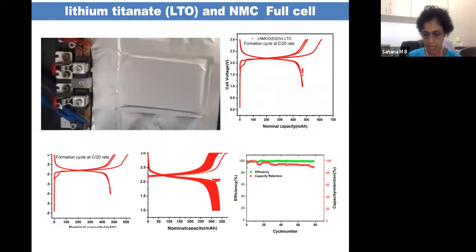Okay. Now, after the formation cycle, this is one example of a pouch cell, where the cathode is NMC, that is lithium nickel manganese cobalt oxide, where nickel is 50%, manganese 30%, and cobalt is 20%. Now, the first cycle here, if you start it, is around 600. In some cases, after the formation, the capacity is only 500 milliampere hour. But after that, during charging and discharging, it remains, because the chemical potentials of both the cathode and anode are within the stability window of the electrolyte. This happens only after the formation cycle. And now if you run the charging, I want you to see this, just a minute.